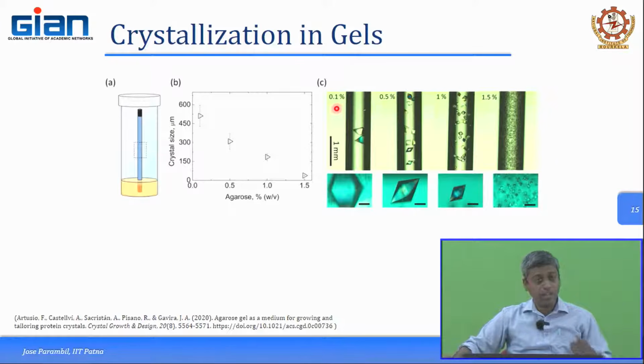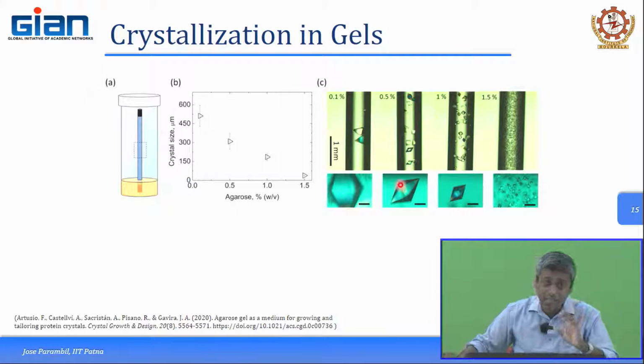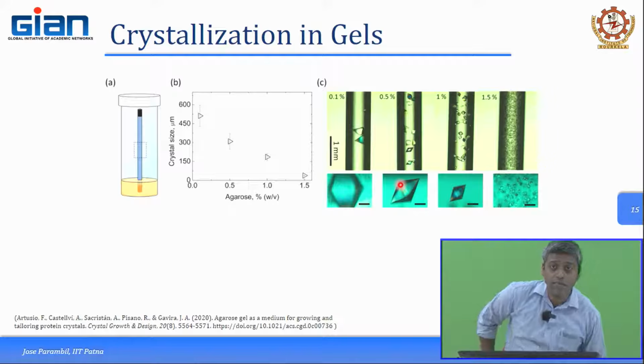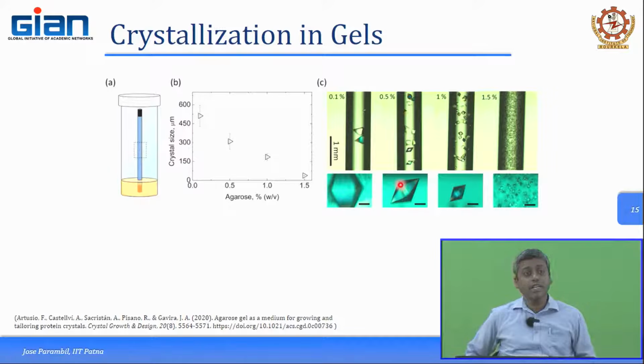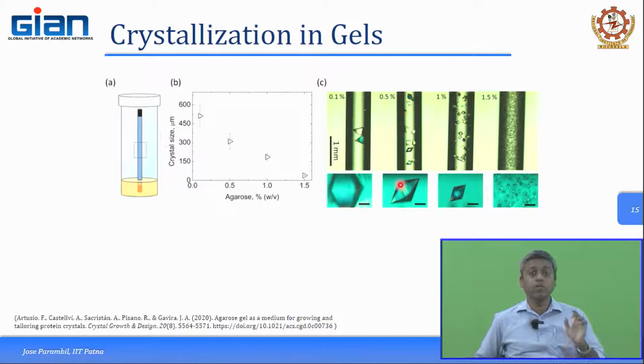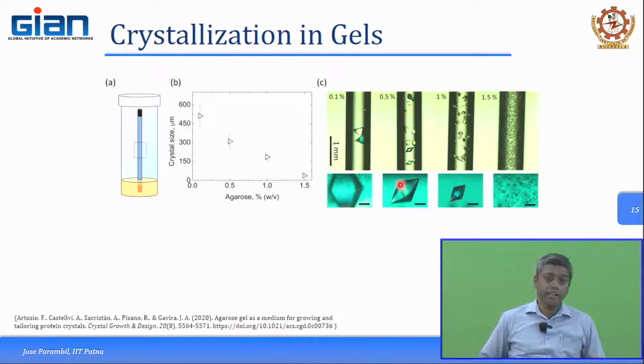and by changing the concentration of the gel, how much agarose is there, you can change the diffusion rates. You can use that in order to manipulate the growth rate or the nucleation rates, and for example, in this case by changing the agarose concentration in the gel, you could produce very large crystals or very small crystals and so on. Now, keep in mind these crystallizations are not done for separation or purification as such, it is primarily done for growing good quality crystals for crystal structure data analysis.